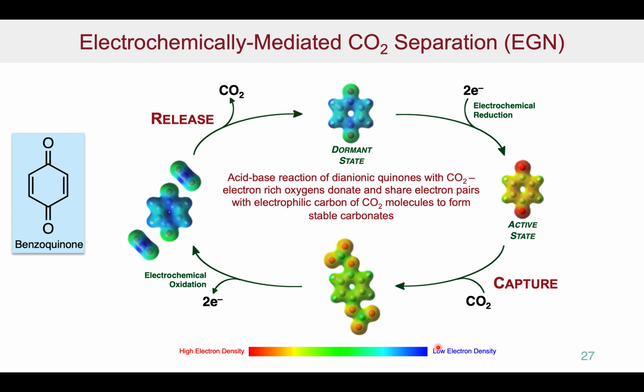Well, there's been some work done in the past by others as well, but we've latched onto this and are looking at the quinone type systems, in which quinone, as shown here in the dormant state, really has no affinity whatsoever. It just ignores the carbon dioxide that's around. However, when you reduce it, it gets very strong electron density on the oxygens here, which provide a very good site for the electrophilic CO2 to be captured to form the carbonate, as shown in this particular case. So we capture the CO2 by the agent that's been electrochemically activated. Once this is fully loaded, we can now take it and oxidize it again to release the CO2 and regenerate the dormant quinone that can be used.